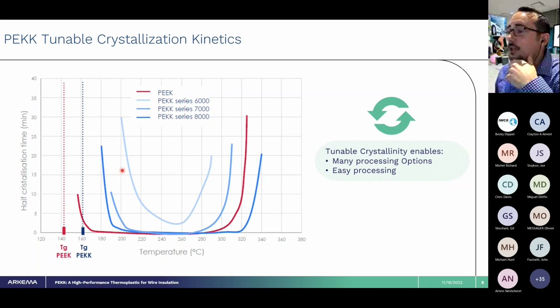Now in our 6000 series, you can see it's much slower crystallization, and to get a high level of crystallization, you really wind up having to do a 240 degrees C anneal, which is really beneficial if we think about some of these thin film processes where shrinkage or warpage may be an issue.